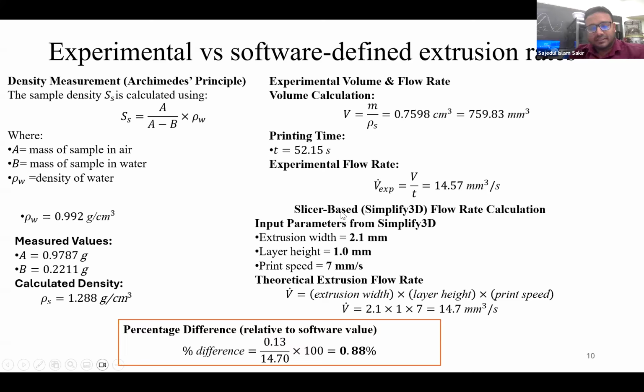Based on this, I got the experimental flow rate. When I was printing it, I kept the predefined Simplify3D values. Based on this formula and these parameters, like extrusion width 2.1 millimeter that I have given in Simplify3D, layer height 1 and printing speed 7, I got 14.7 from the software, and from our experimental density-based measurement, I got 14.57.